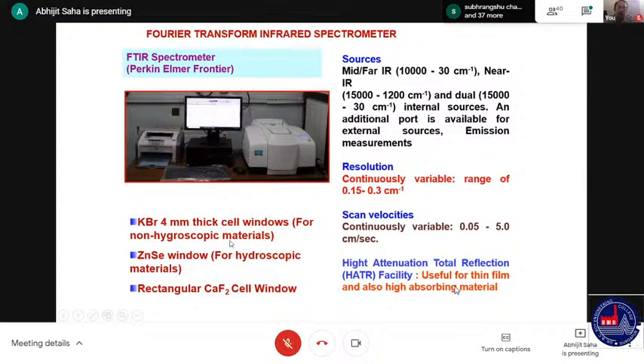Normally for IR we use a KBr window, which is a potassium bromide window, but potassium bromide is very hygroscopic. For hygroscopic material, it is not useful. So we have to use the zinc selenide or the calcium fluoride window.